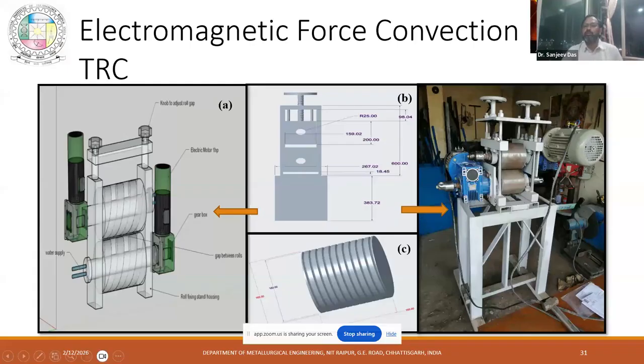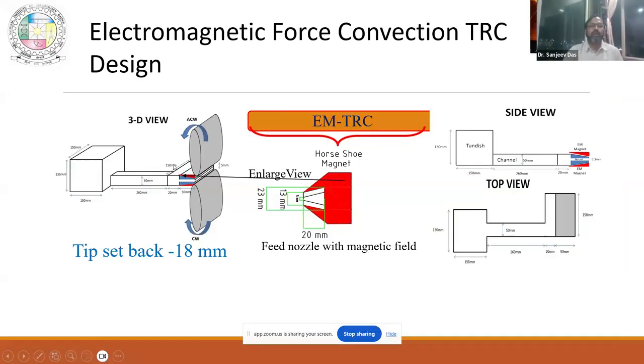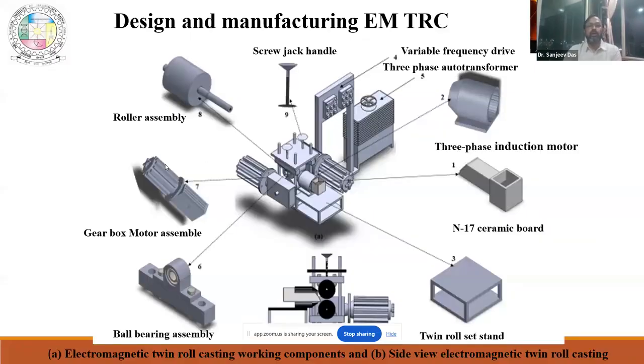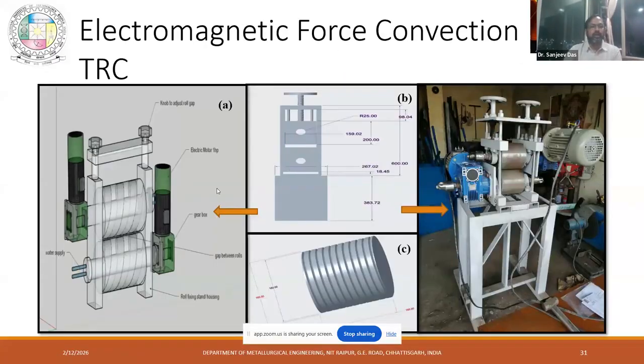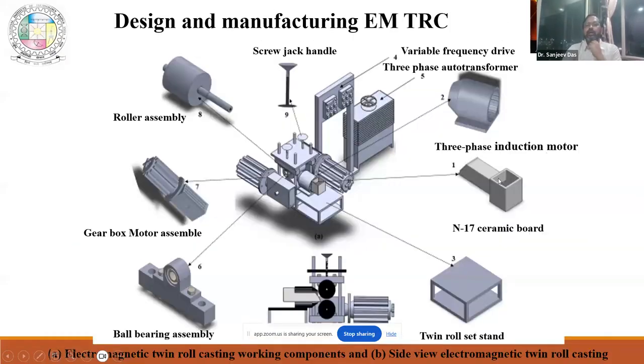This is the twin roll caster which we have designed and manufactured in our lab, and we have put some electromagnetic arrangement in it for when we are putting in the liquid metal. Now let me show you our design. Here there are two rolls inside, in the roller assembly, and these are internally water cooled rolls. You can see there are grooves on the rolls inside. The water runs in these grooves, and there is a sleeve at the top, also water cooled. So the temperature is completely maintained, right? Then you have the tundish here from where you put the liquid metal, and the magnetic field is there, which will rotate the liquid metal during the solidification process.